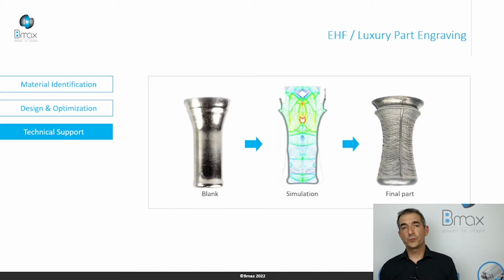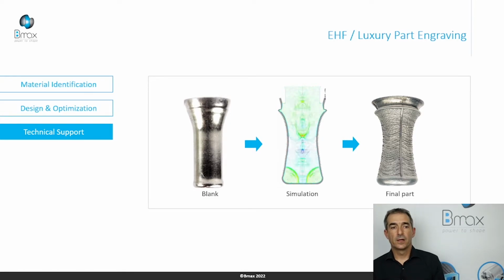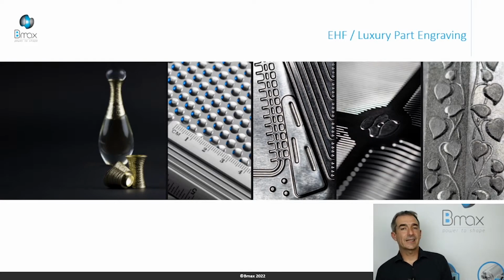In the real world, we use exactly this preformed geometry with the bump in the bottom. And we have the sharp details; the depth of the sharp details is around 1 micrometer. So, as you understand, for this kind of application, the preformed geometry is the key point. We have to optimize this preform to define the optimized initial condition for EHF. We are able, with EHF, to create new texturing, to engrave complex parts with very high marketing requirements. And we can form any products like fragrance caps, jewelry, luxurious packaging, cosmetics, and luxurious decoration, for example.